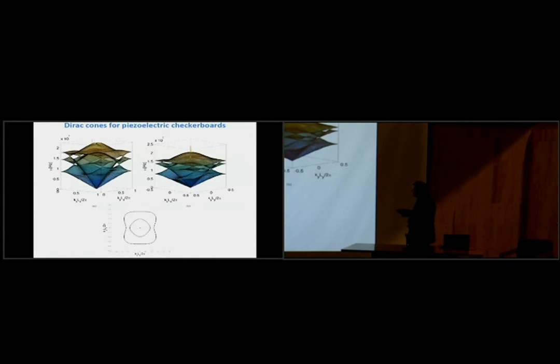Of course, the slope of the cones at the origin is higher. That's not surprising because you do have piezoelectric stiffening. But in addition, you can see quite substantial change in the higher order dispersion curves. And one interesting thing is, as you can see, there are some conical points on the dispersion surfaces. These are known as the Dirac cones. And Dirac cones give you locally neutral medium if you talk about transmission problems. And really, position of the Dirac point tells you about the angle of incidence and the frequency of the incident wave if you have a stack of checkerboard-like material, if you want to see pretty much undisturbed propagation through this.